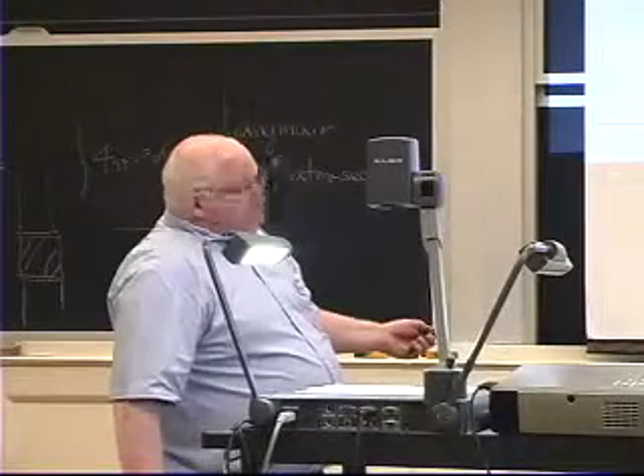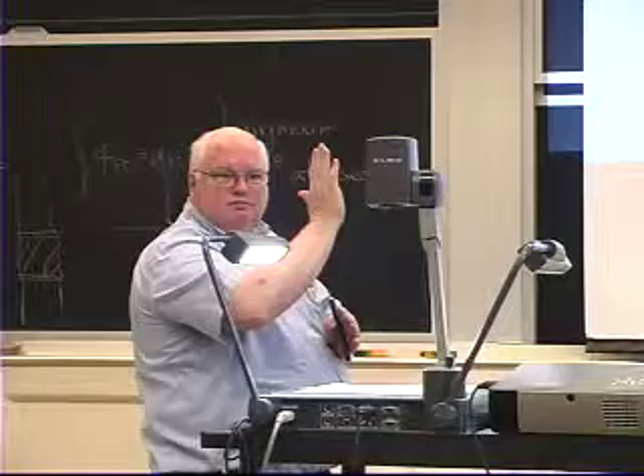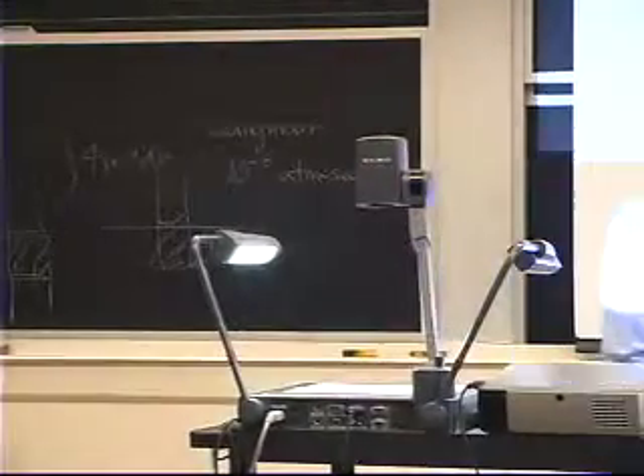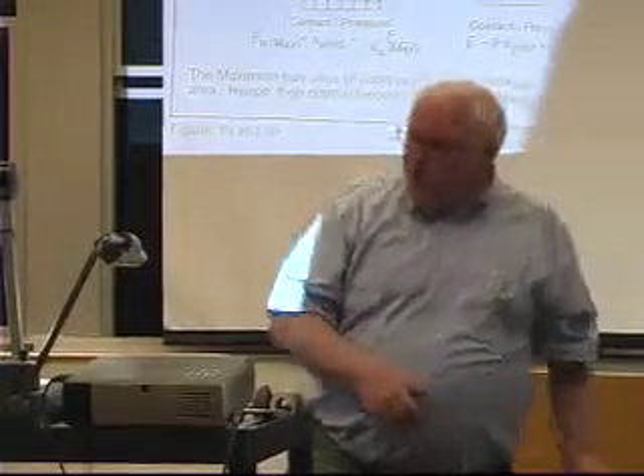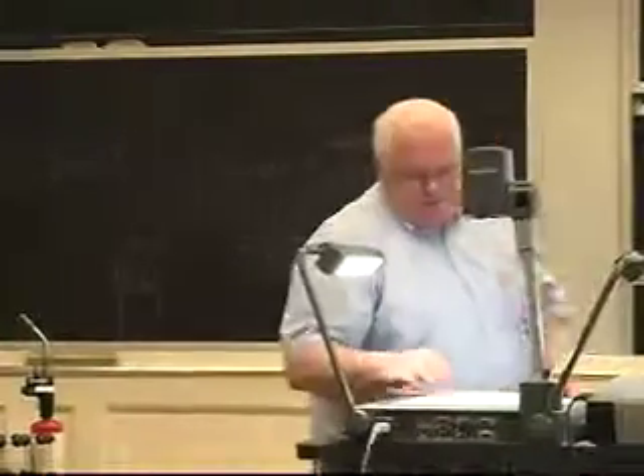The only way you can really get rid of those voids that are trapped in there is to shear the material. And that's what you're doing with the friction weld, right? You're getting rid of all the surface roughness and the contamination by just extruding the material out of there. Okay? Now, you can also use a soft material, and this graph should be in your notes. There's a paper by Tylecote in 1954 in the British Welding Journal, Investigations of Pressure Welding. The key graph is this one right here, which like I say is in the handouts: the oxide to metal hardness versus the amount of deformation of the material.